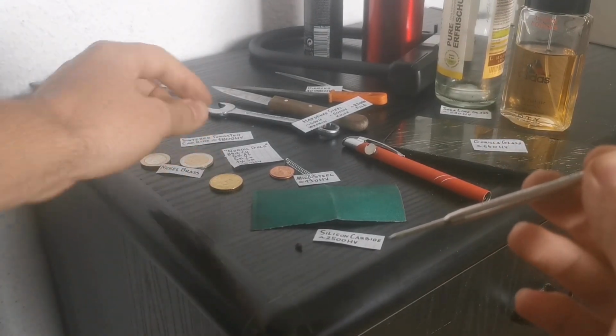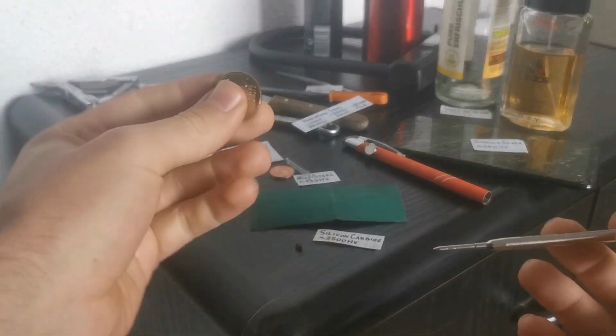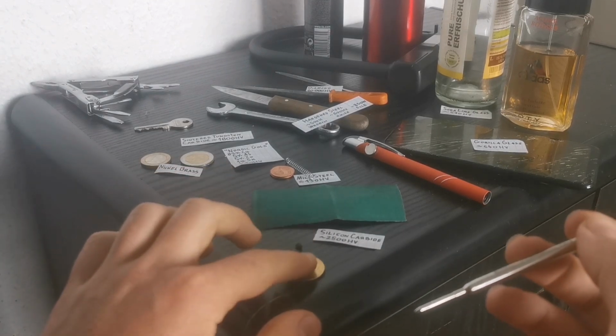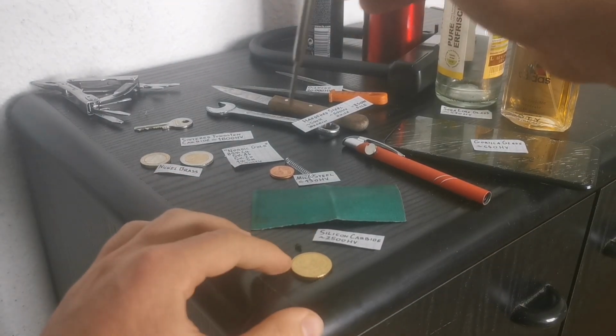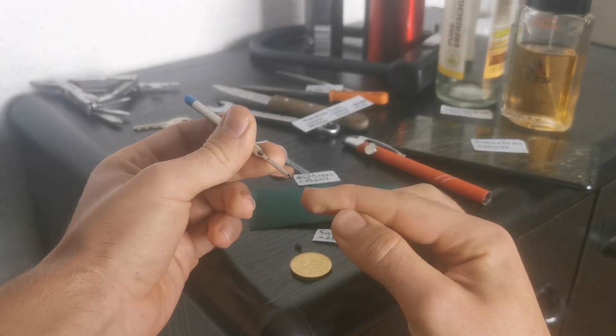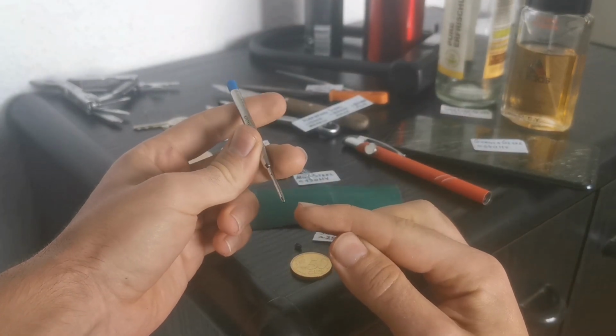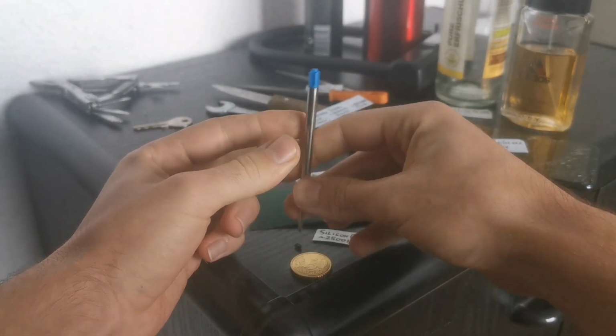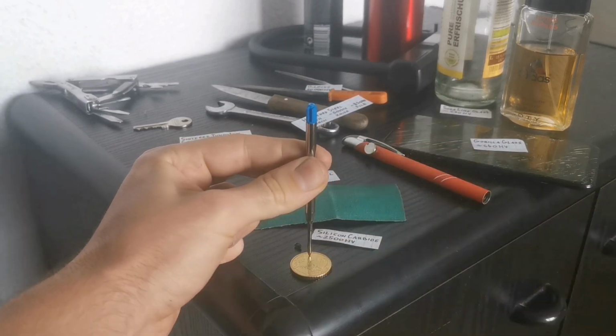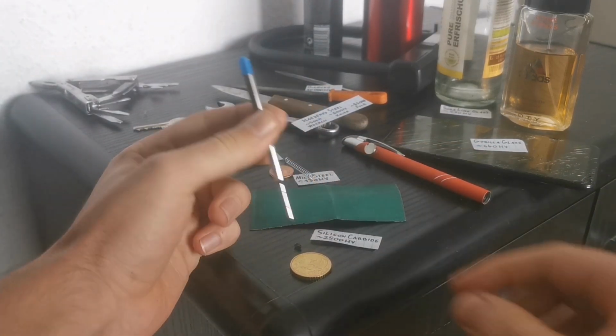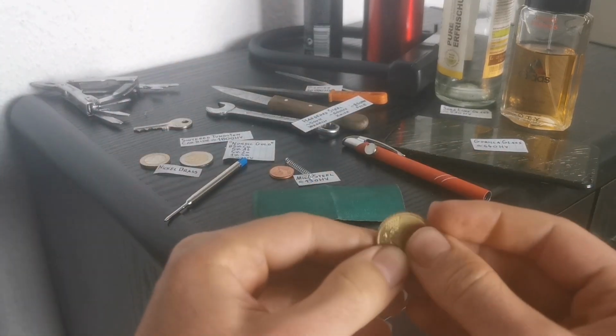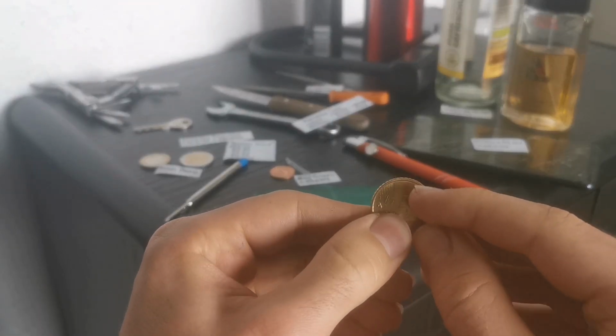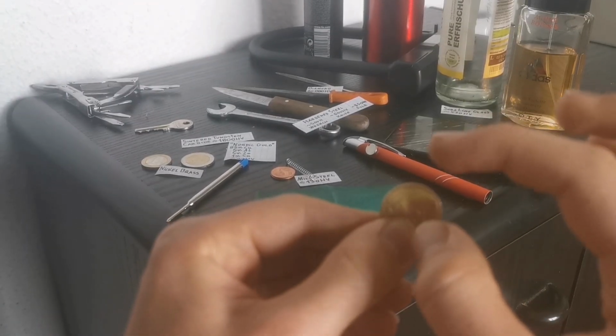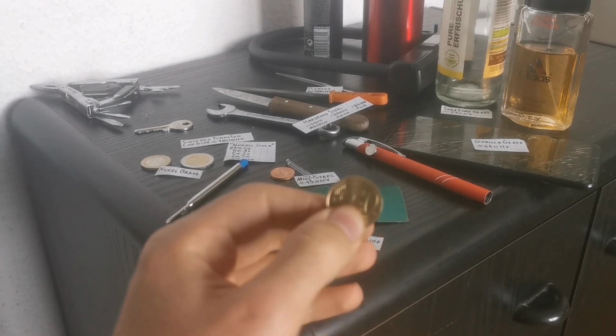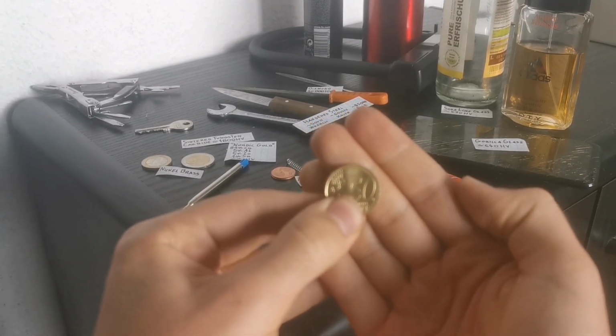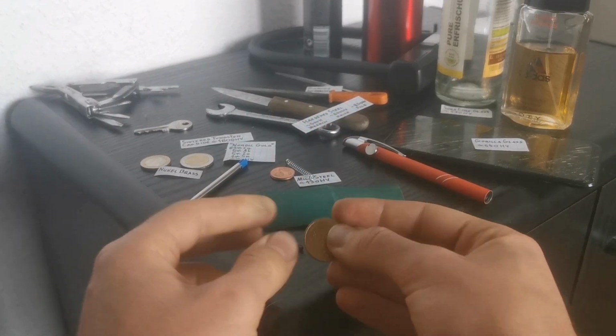I will replicate the Brinell method, where an object that needs to be tested is laid flat, and then a ball with a known diameter, here it's 1 millimeter, is pressed into this object with a known force, and after that the indentation in the shape of a circle is measured, the diameter is measured, and in such a way we can calculate the hardness of the base material.